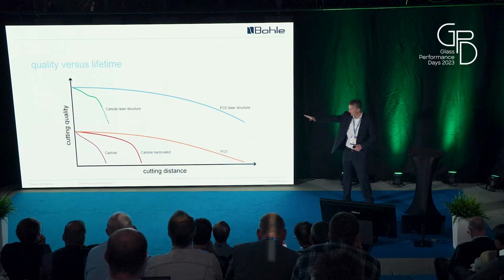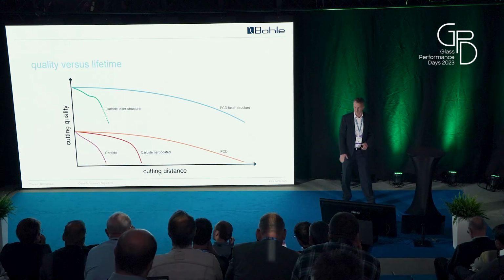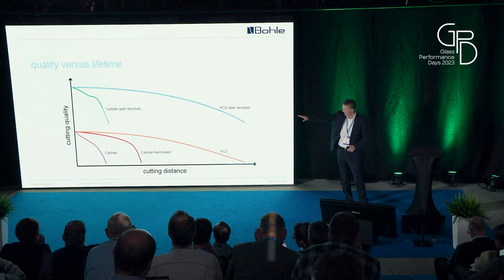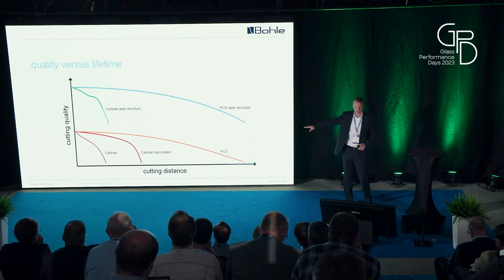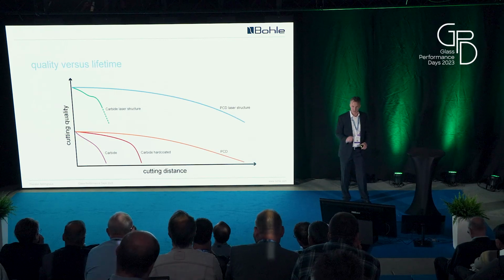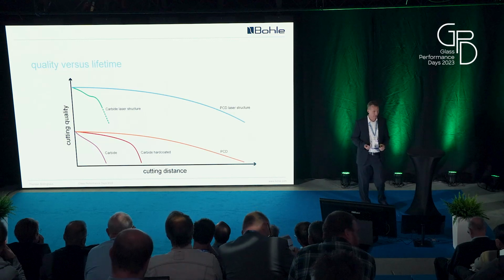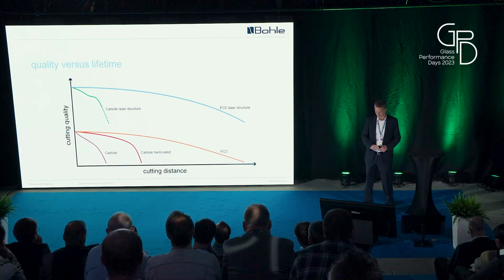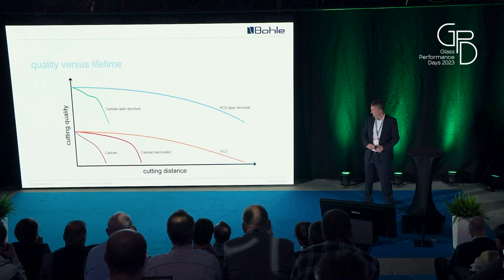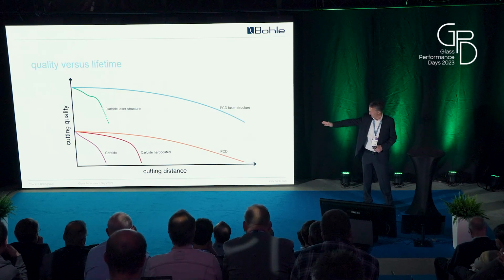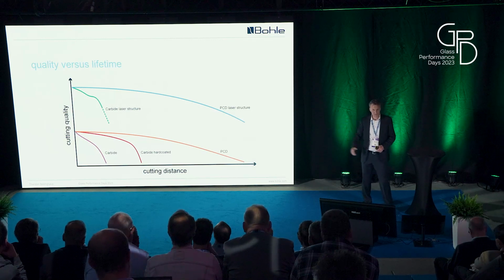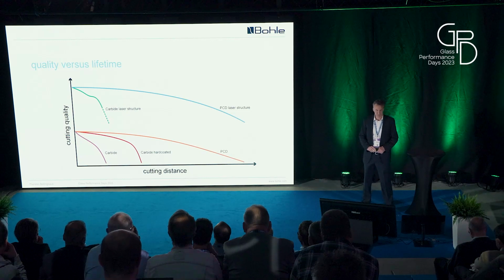Then the blue line is the PCD wheel, which has a much longer lifetime. And what is interesting also, it has very stable conditions in the beginning. So the line wants to indicate that you don't have to modify your cutting parameters so quickly. So this can be interesting. And in between is the carbide hard-coated wheel. It's really in between of the 2.